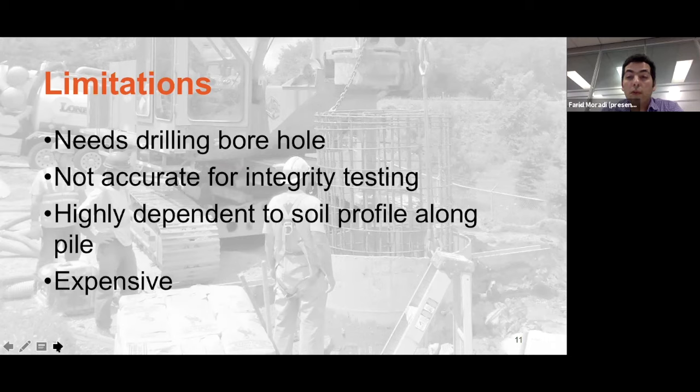It is highly dependent on the soil profile, the geology along the piles. The soil profile can change a lot. We had a project where I worked with some colleagues: for just 10 meter piles, the soil profile changed five times from very poor condition to very solid rock. Such a condition makes data interpretation difficult using that technology. And it's sometimes expensive because it needs at least a few boreholes drilled near the piles for condition assessment of the piles.